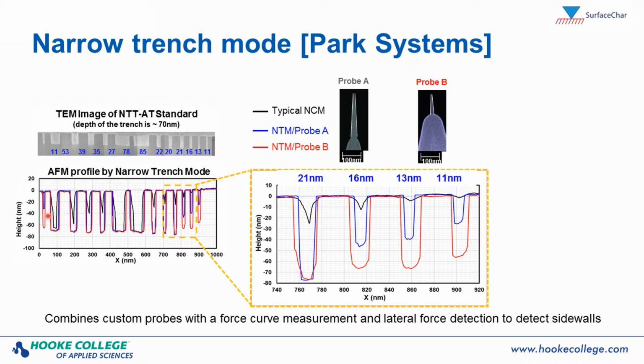And these are what the probes look like. There are two different kinds of probes here that are showing data. You can see very high aspect ratio, right? So this is probe A, and that really is this, the blue, gives you the blue outline for these trenches. And you can see it not quite getting in and getting the depth or the width of these trenches. And then probe B, and these are both custom probes designed for this technique. Probe B does appear to do better. That's following the red line here.